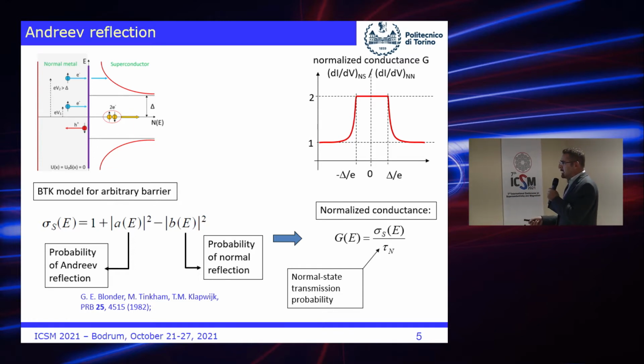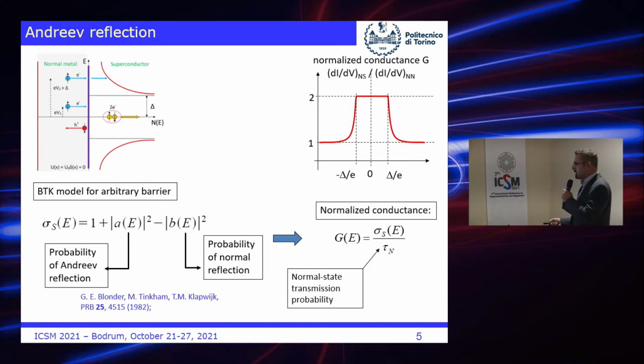All these four processes are taken into account within a model given by Blonder, Tinkham, and Klapwijk already in 1982, in which the superconducting state transmission probability can be calculated as a function of the probability of Andreev reflection and the probability of normal reflection. These two quantities contain the amplitude of the gap, of course, and this, once divided by the normal state transmission probability, gives exactly the normalized conductance, which is actually what we measure.